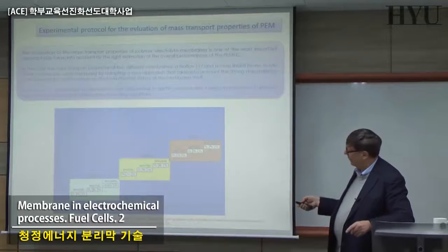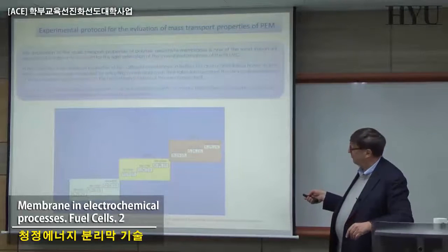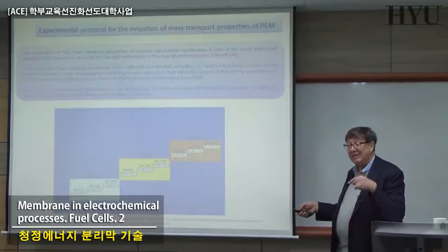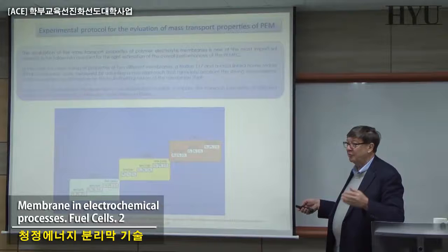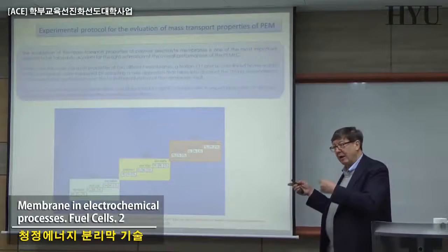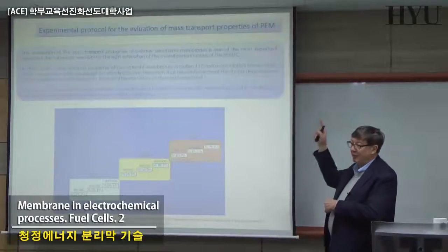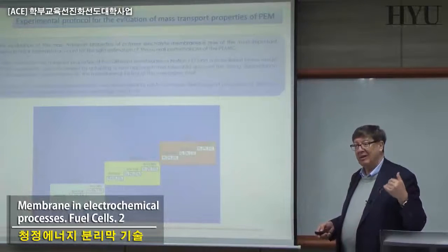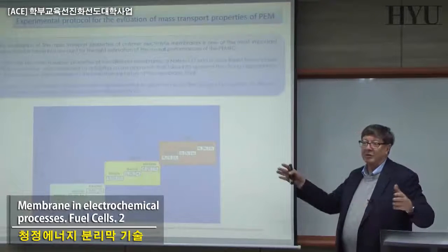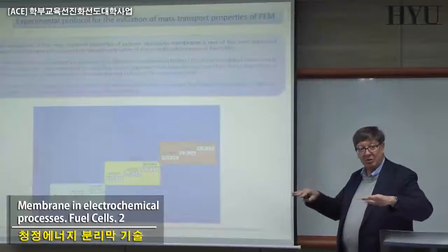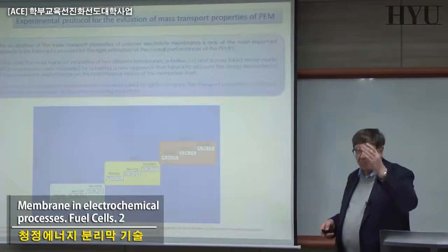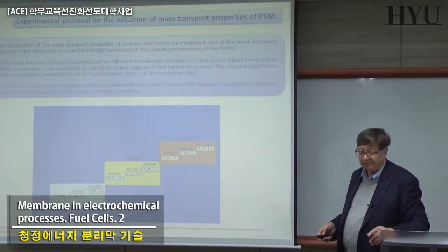And these other fluxes can have different behavior depending on the relative humidity and on the way in which you are measuring. For example, the history of the experiment. If you measure first at low humidity and later at high humidity, and the others start from high and go to low, you can have different results, because there is some hysteresis and some history still exists. Normally you don't wait for months or years to reestablish the same condition, so the methodology, the protocol that you follow, going up or going down, can give you different results.